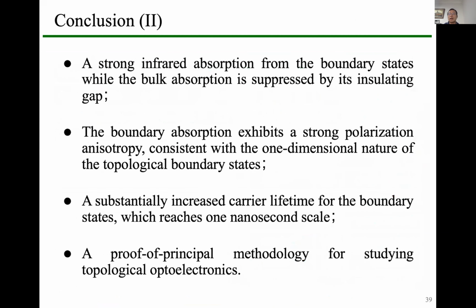So in this section, I have shown you a strong infrared absorption from the boundary states, but the bulk absorption is very weak. The boundary absorption exhibits a very strong polarization anisotropy, consistent with the one-dimensional nature of the topological boundary state. We also observed that the lifetime is very, very long, about a nanosecond scale. So we also use this to make some very preliminary proof of principle devices for optoelectronics.